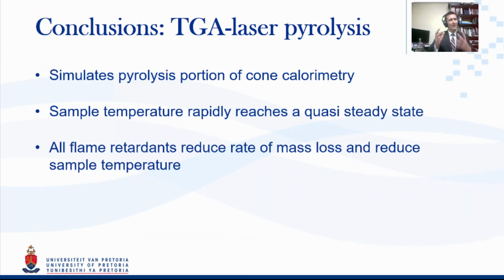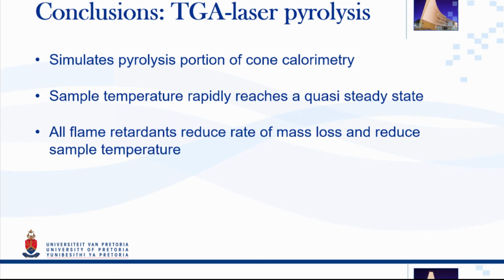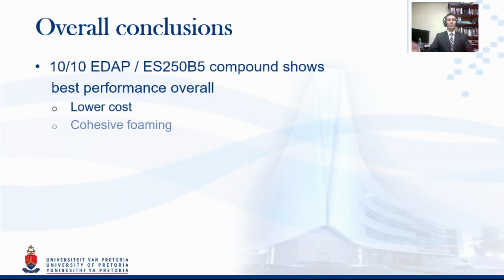In conclusion, regarding the laser pyrolysis, here we've simulated the pyrolysis portion. It reaches that same rapid temperature rise and a quasi-steady state, and all flame retardants delivered good mass loss resistance. So this, I think, indicated to us that this is definitely a good method for testing, on a very small scale, a lot of new materials very rapidly. Now I'll go to the overall conclusion.